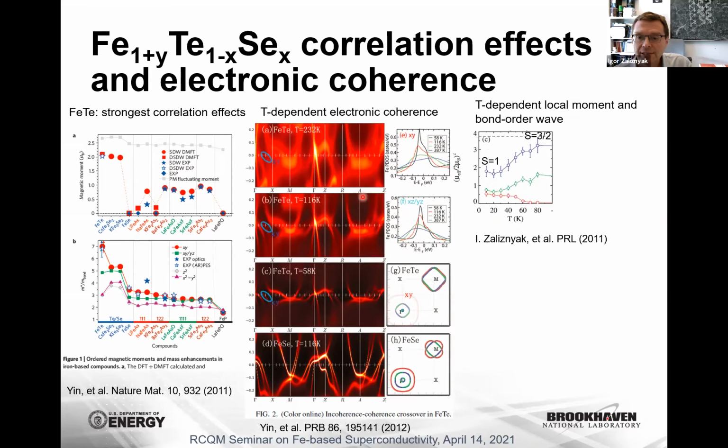That was actually consistent with our earlier neutron scattering work, where we observed a change in the total magnetic scattering that can be assigned to local moment fluctuations, from local moments corresponding to spin 1, or 2 localized electrons, at low temperatures to local moments of spin 3/2, or 3 localized electrons, at high temperatures. So this is in agreement with 1 electron that gets coherent upon cooling, leaves its local moment localized state and goes into a conduction band.